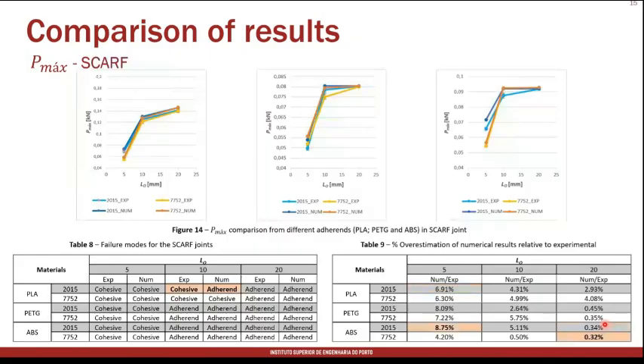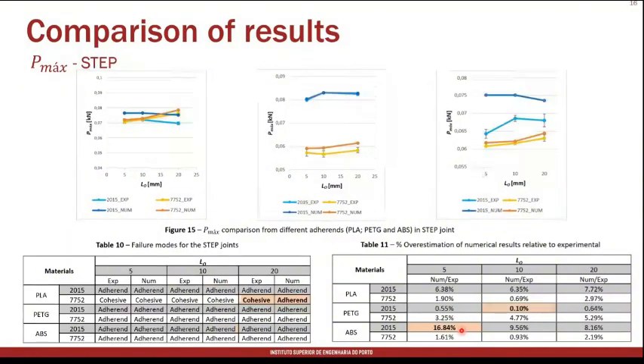And if we move on to the scarf joint, we can also see that there is a good correspondence in terms of failure mode. One condition in which the experimental failure was in the adhesive, while numerically it occurred by plasticization in the adherent. And once again, we have a higher failure load between 5 to 10 millimeters than between 10 to 20 millimeters. Maximum error was also below 10% in this case.